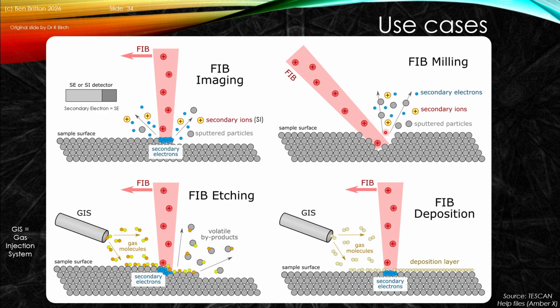And so in this case, we have these sputtered particles. As they get ejected from the FIB space, they get redeposited behind the beam, and it's kind of like digging a hole on a beach. The sand can pile up next to the hole. It can make it difficult to dig deeper into the beach itself. Well, if you attach a volatile byproduct to the side of it, you can enable those things to effectively float off and not adhere back to the surface. And that's what the FIB-enhanced etching approaches enable us to do.